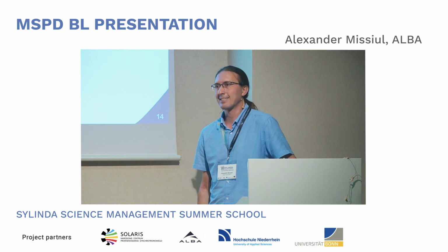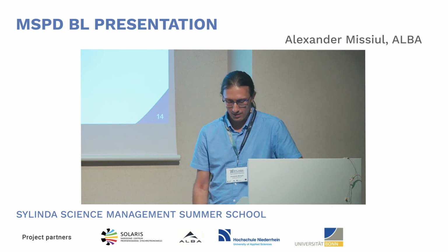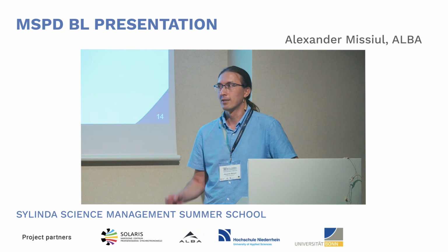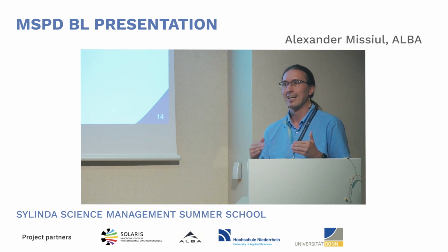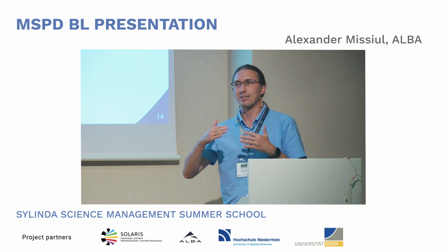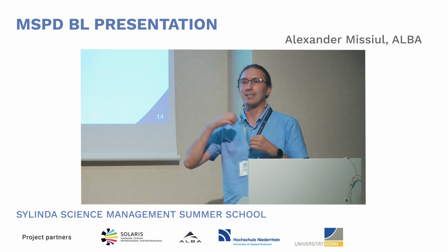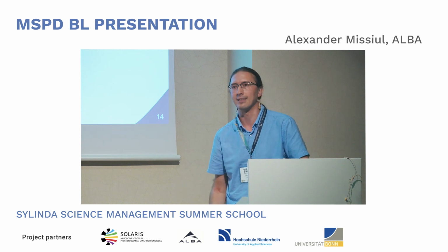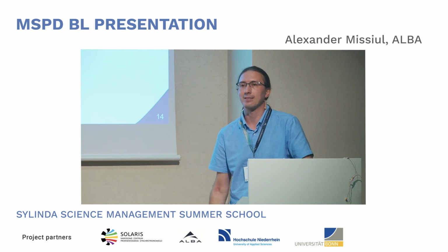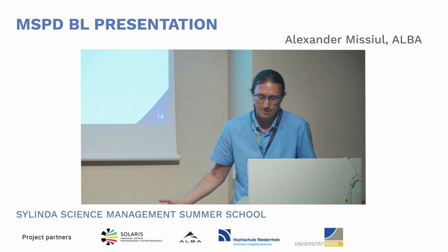And to analyze this, modern X-ray analysis software has this option of so-called sequential refinement. So you start with really refining your starting structure or composition of your starting mixture. And then, because each next pattern differs only very little from the previous one, it can be automatically adjusted. And so using this, you immediately, in a few minutes, have refinement results of hundreds of patterns. This exists at the moment, and we can use it.